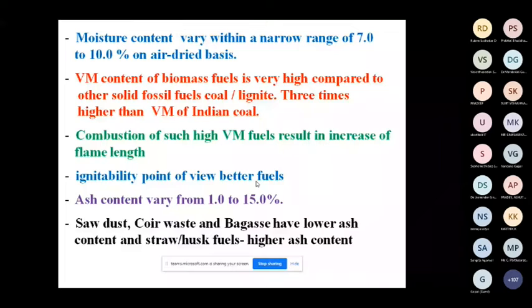Ash content varies from 1% to 15%, compared to coal, where even a better coal has 25%, and the variation goes from 25 to 50% ash content. So in that respect biomass fuel is a cleaner fuel, with an ash content of 1 to 15%. Among the biomass fuels, sawdust, coir waste and bagasse have lower ash content, and straw and husk fuels have higher ash content.